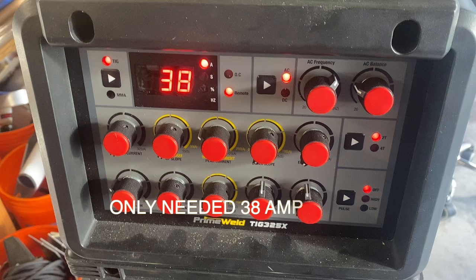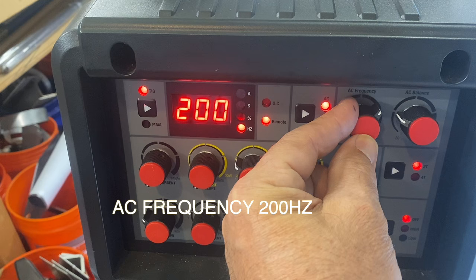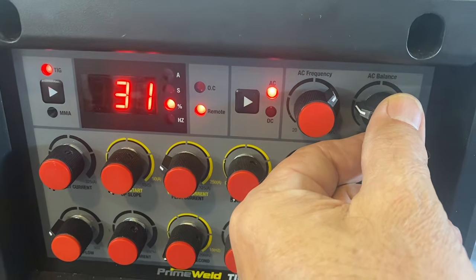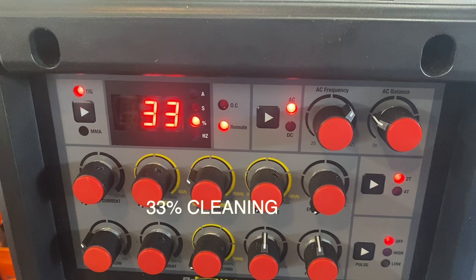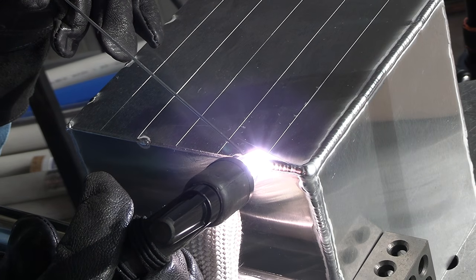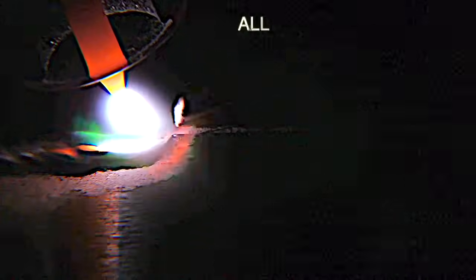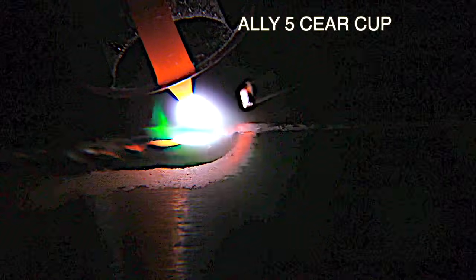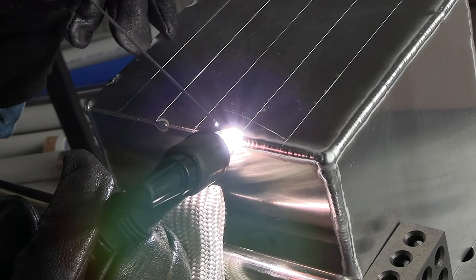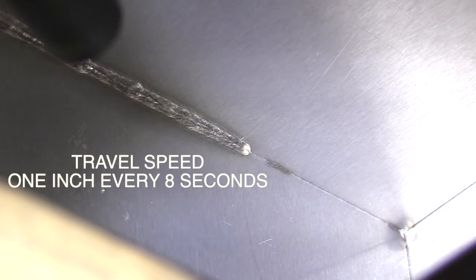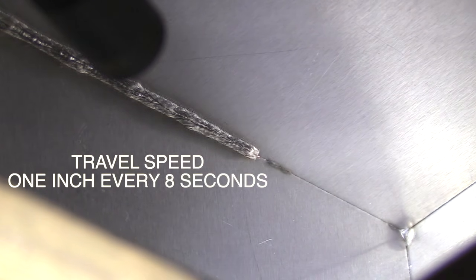I only needed about 38 amps for this because there were some little tiny gaps in the fit up. I used 200 hertz on the frequency, 33% cleaning. And I use a little technique that looks something like this, where I just raise the arc a little bit when I'm adding filler, and I back up just a little bit, because again, there are some tiny gaps in this, and as I backed up while I added filler, that kind of prevented me from keyholing out or blowing through.